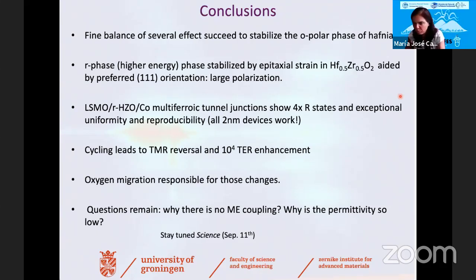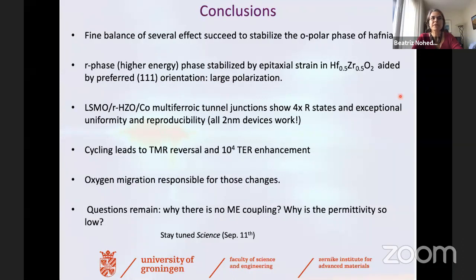Well, that question was from Guanse Chen. And there is another question from Beth von Cuberta. What is known about the role of surface energy on the stabilization of the rhombohedral phase? Yeah, so that's a very interesting question. We think that it must have a very important role, probably similar to the orthorhombic phase, because we see the same effect that above 10 nanometer, the films become a mixed phase. Of course, the thickness of the film is correlated to the size of the grains that you form. So grains above 10 nanometers are difficult to stabilize in single phase rhombohedral. So it must have an important effect. So maybe that's the answer.